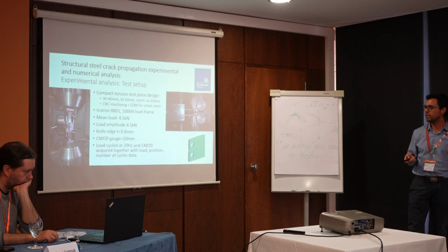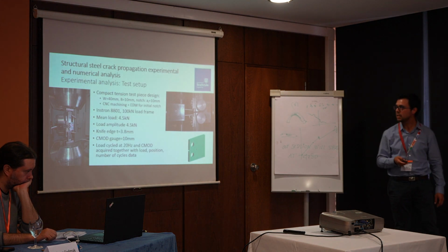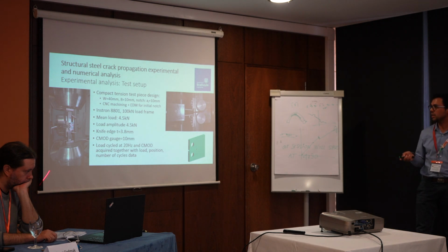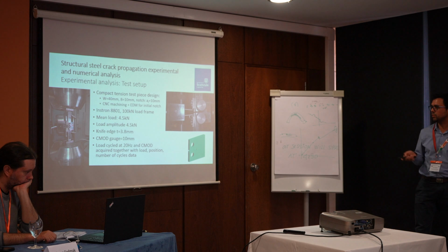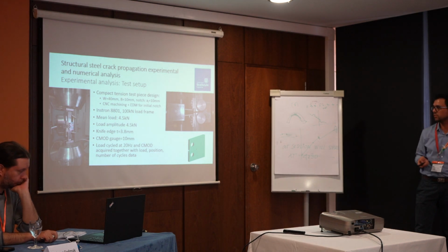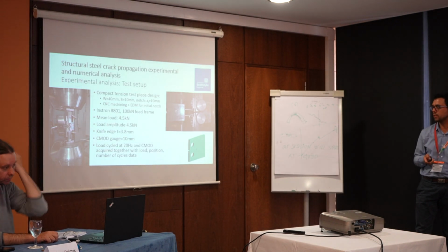So here are some of the setup parameters that we use for this lab test. We used a sample with a width of 40 millimeters with a notch of 10 millimeters. And we used the Instron machine with a mean load of 4.5 kilonewtons and a load amplitude of 4.5 kilonewtons as well.